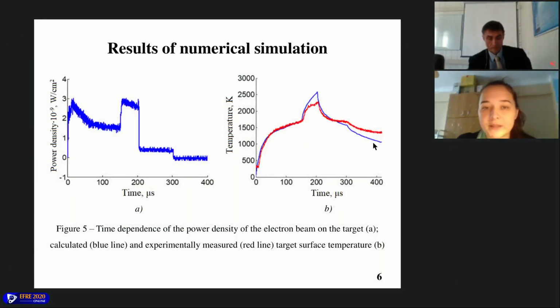Back to our main experiment with steel. You can see on slide 6 the result of numerical simulation, namely figure 5b shows the dependence of target surface temperature. The red curve is the experimental one, and the blue is the calculated one. You may see that there is a satisfactory agreement between the experimental data and calculated data. The peak shows the end of the pulse.